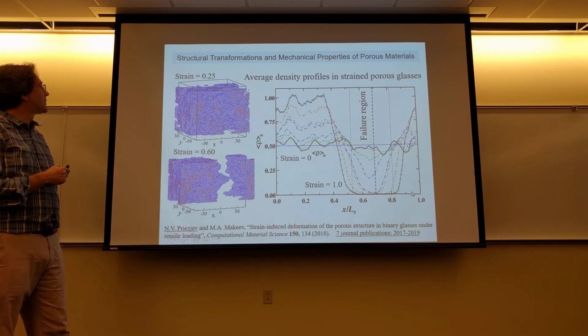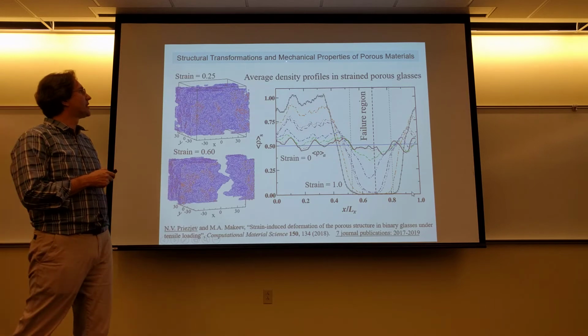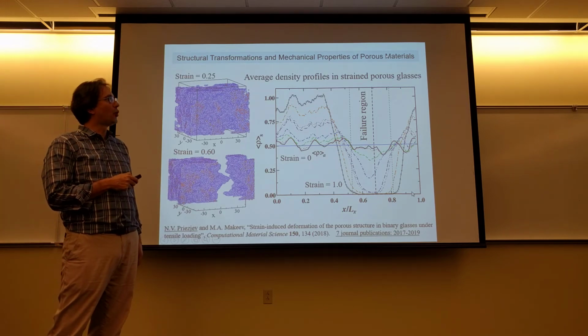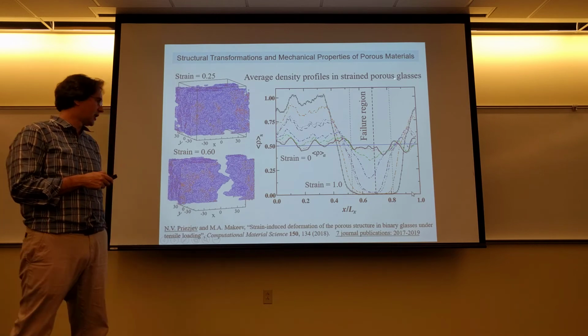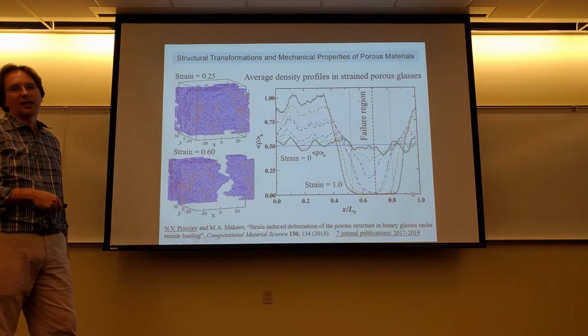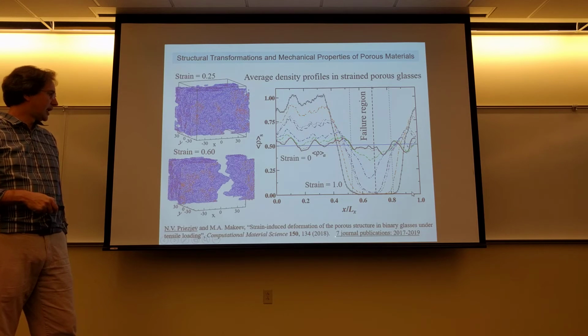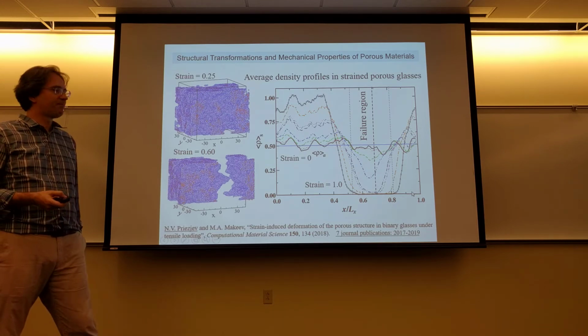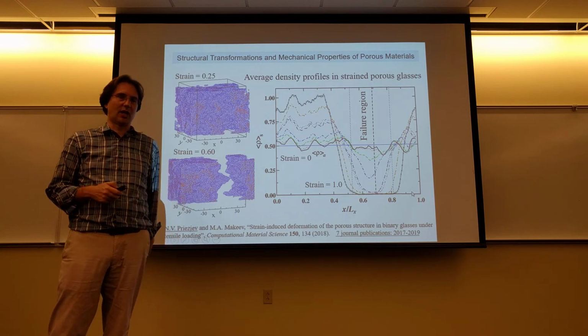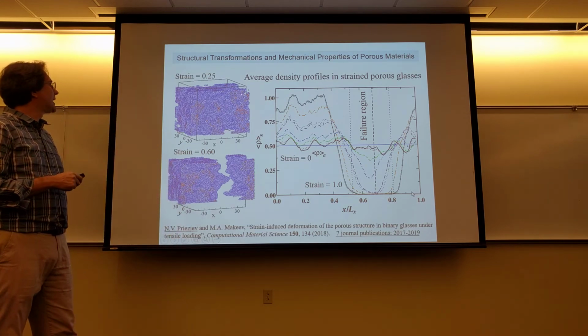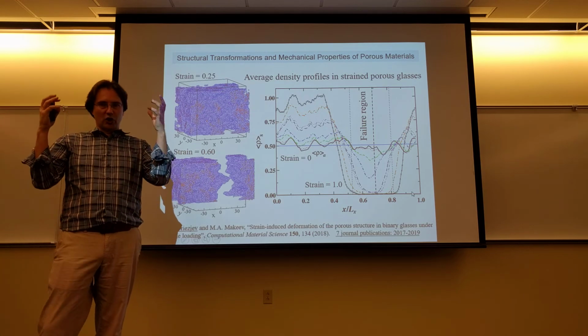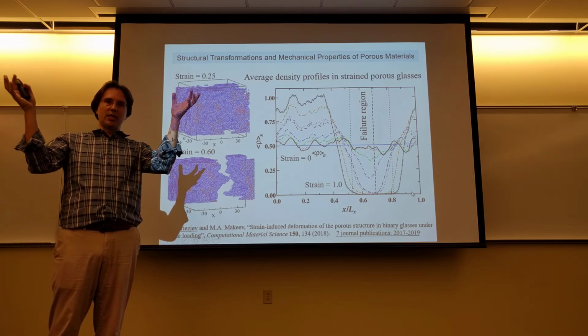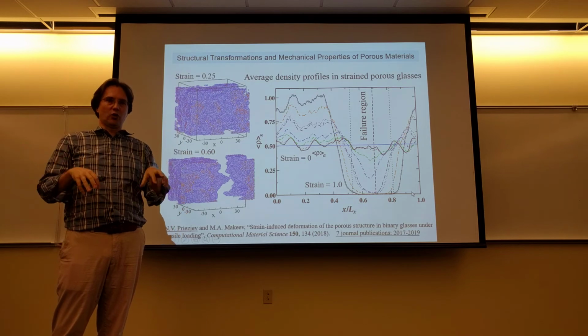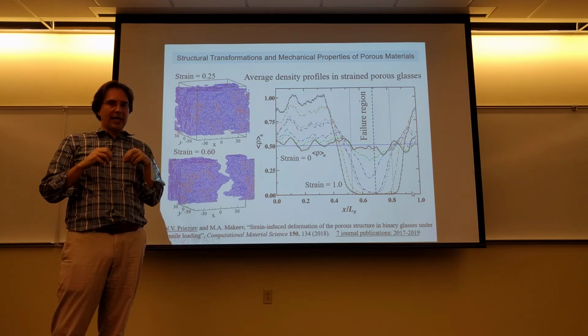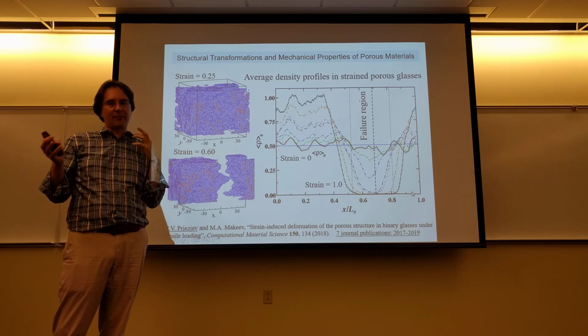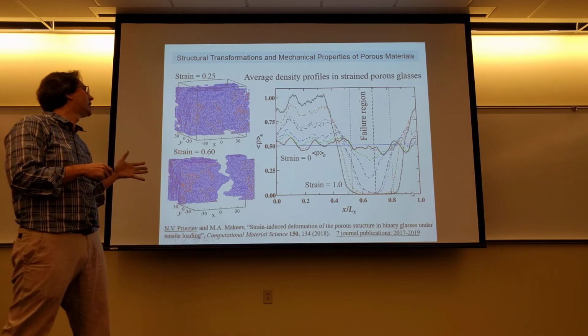Good. So we now switch gears and consider the topic that deals with structural transformations and mechanical properties of porous amorphous materials. This research was done with a colleague of mine, Maxim Makeyev, and in the last couple of years we published 7 journal papers on this topic. In general, we consider a special system which is a good glass former, and we quench this rapidly to a lower temperature at constant volume, and in such a process phase separation and solidification take place,